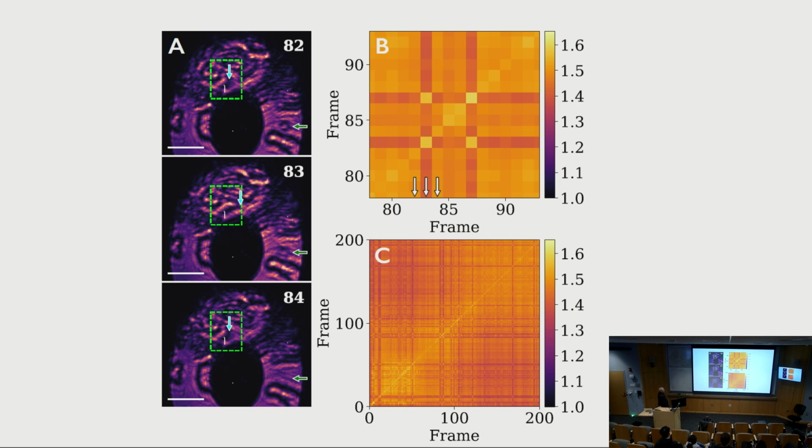I have shown you an example of directed motion, where this bulge and protrusion was moving in one direction, but a more typical type of behavior is actually switching behavior, when you have the domain wall going back and forth, as in this image. This is the so-called two-state switching behavior, for which one can also make the corresponding two-time correlation function. You see only lines of a certain width, in this case indicating that indeed the switching occurs very quickly, on the quickest possible time scale. You go back and forth.